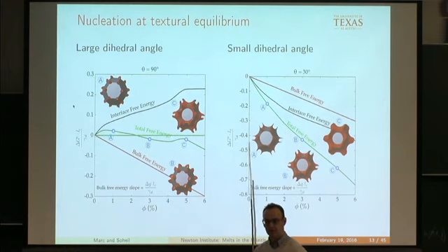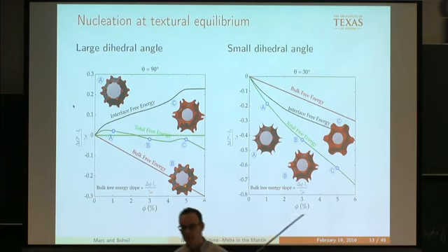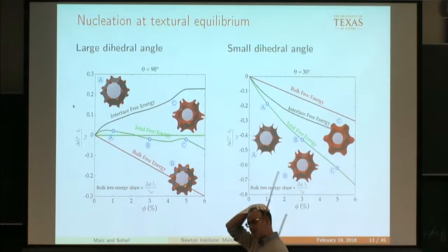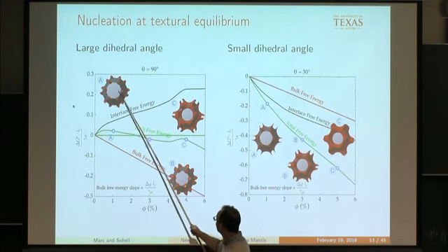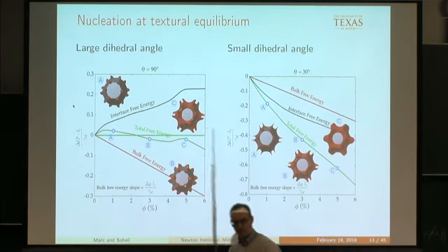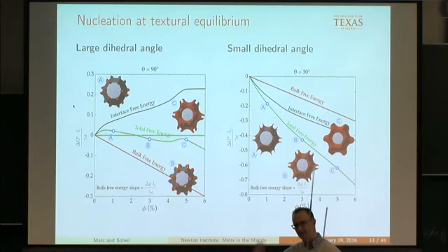Yes? I've really missed this, but you're essentially calculating nucleation on 4-grain junctions. That's where the nucleation starts. That's why 70 degrees matters. On 3-grain junctions. Yeah, so along these edges, 3 grains come together, right? And then at the corners, 4 grains come together. But your nucleation starts at the 4-grain junctions.